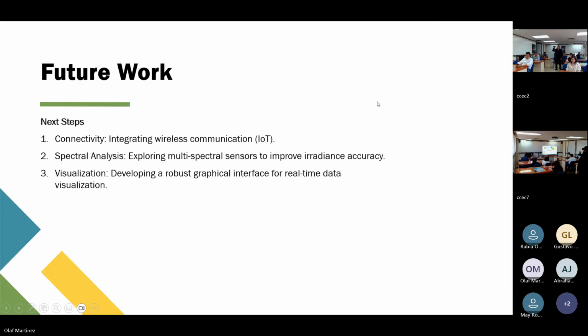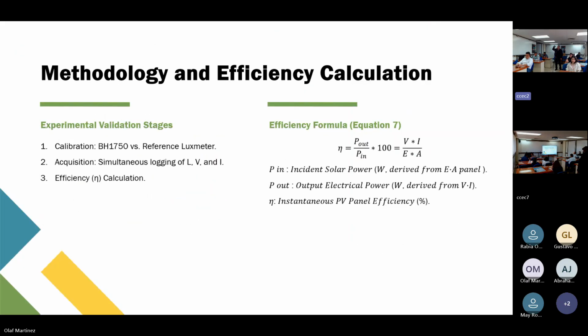Well, it would be good to have an idea of the nominal efficiency of the module, what the provider of the module gives you as the efficiency. You say that you measure the efficiency and you get a variation between 7 and 13%. So it would be interesting to know what the nominal efficiency is. Well, yes, it would be better to have the nominal efficiency, but we use a very simple equation.